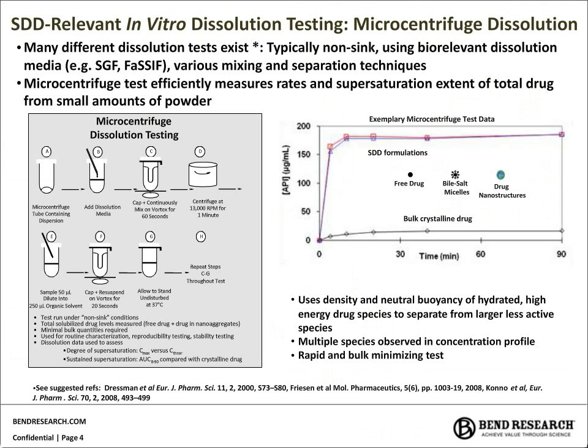So with that detailed description, we look at one major test protocol we use to characterize those species. Most of these tenets are very similar to literature tests, though. This is a non-sink microcentrifuge dissolution test. We commonly use biorelevant dissolution media, including transfers if necessary. Various mixing and separation techniques are out there, and this particular protocol allows us to use suspension or powder dosing. The key is to separate the three major species representing total dissolved drug from that precipitate or undissolved material.